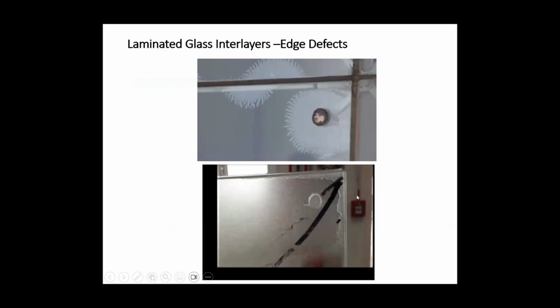Okay, so one of the issues with laminated glass that you should be aware of, unfortunately this is not common, is to see if there's any delamination where the glass is separating from the interlayer. So the picture on the top looks like a point supported system. You can see around the point there is what looks like a white star. That is the glass separating from the interlayer. And then above that, where I think this is structural sealant, you're seeing delamination as well. And then the bottom is a piece of glass showing delamination on the edge.